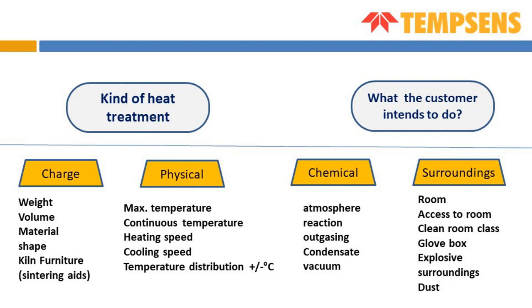So based on that, we can define all the programming through our controller setting, advanced controller setting: the heating speed, cooling speed, your ramp time, your holding time. The furnace itself should also have uniform temperature distribution throughout the furnace. That also varies, because with lab-type furnaces like a muffle furnace or high temperature furnace, for 20 liter or 50 liter, you will get temperature uniformity of approximately plus or minus 2-3 degrees.